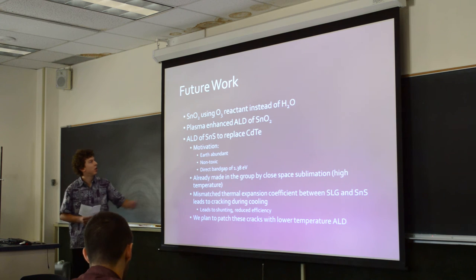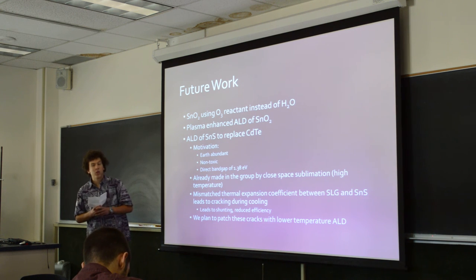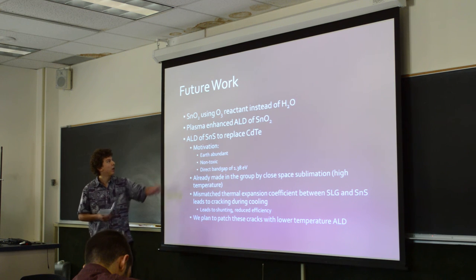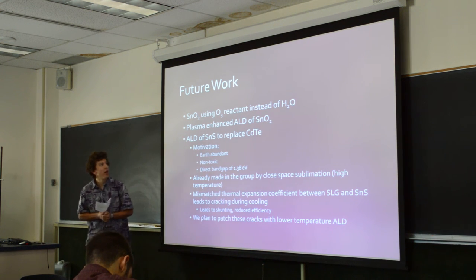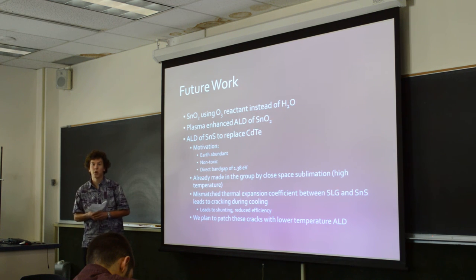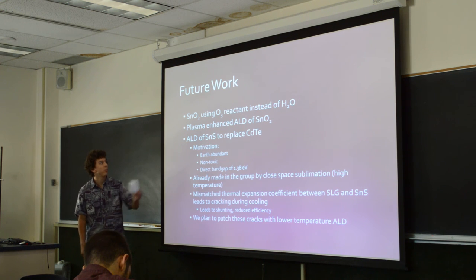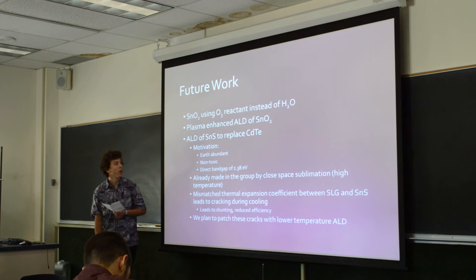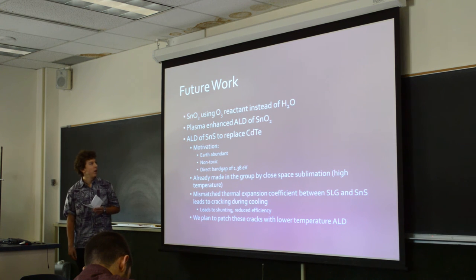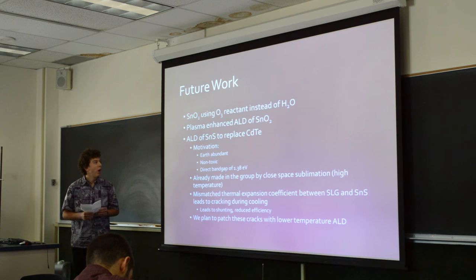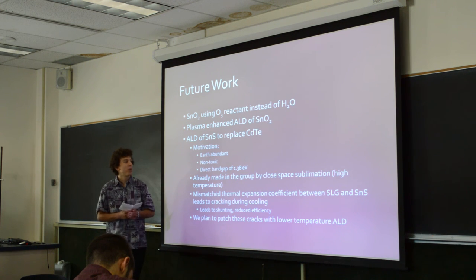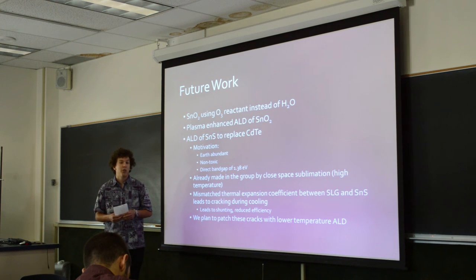In the future, we'll be using ozone instead of H₂O, hoping that boosts our carrier concentration. We might also try plasma-enhanced ALD, which allows us to use a lower substrate temperature because the energy necessary for the reaction comes from the plasma rather than the thermal heat of the substrate. On a completely different note, we're going to try to grow tin sulfide to replace cadmium telluride as an absorber and see if that works.